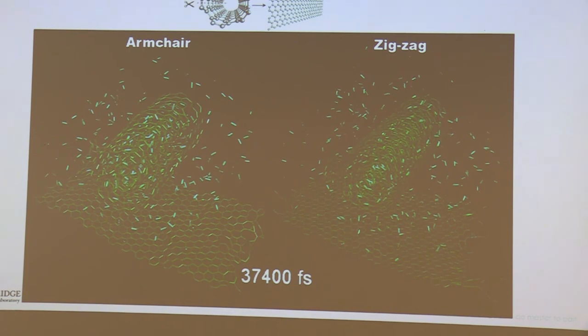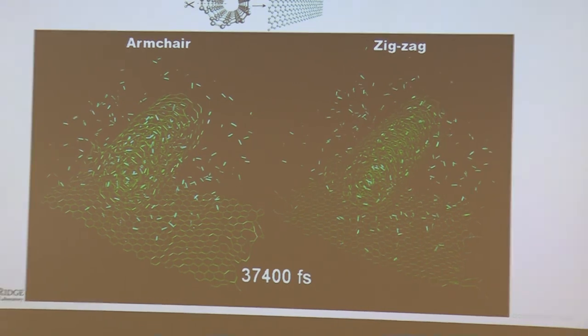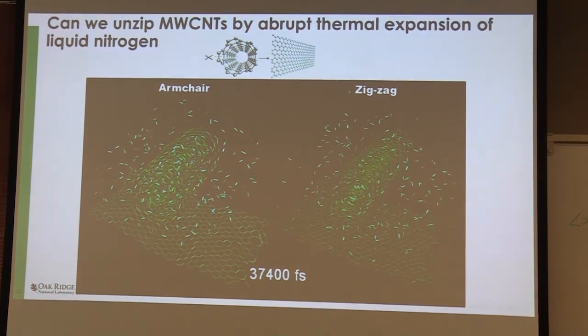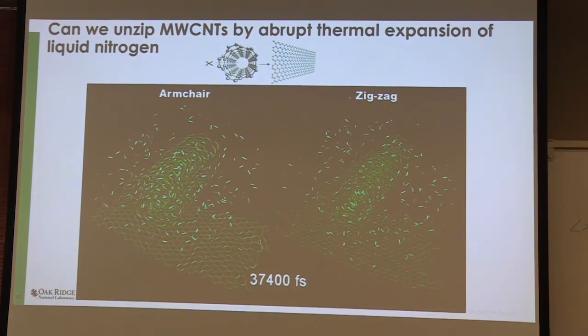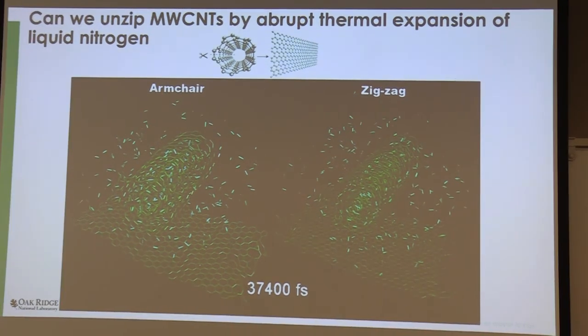There's a fault structure that goes through cylinders, and that's how they fracture. But indeed, we could produce single layer graphene ribbons of a very controlled width using this unusual nano hot dog approach. Experimentally confirmed, and experimentally they've been able to make quite a large amount of this material and validate it. So another example of using these techniques to solve problems, and that would be very exciting.